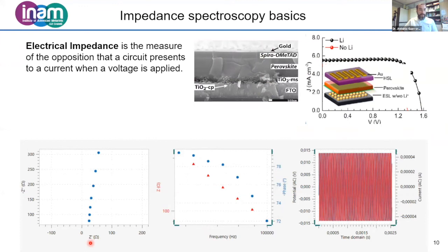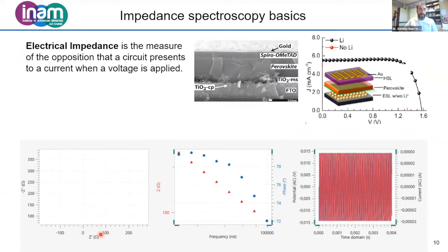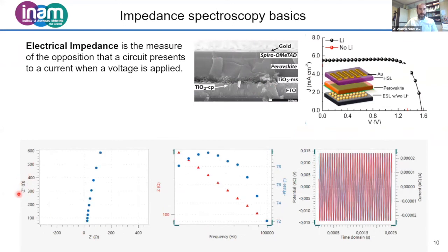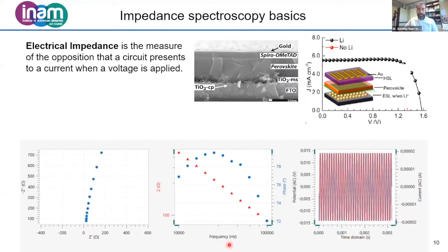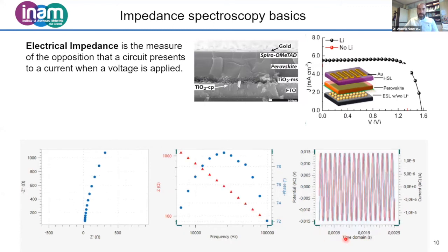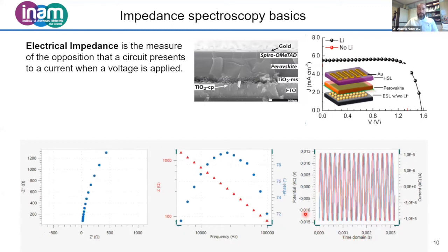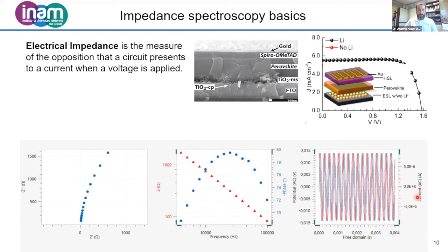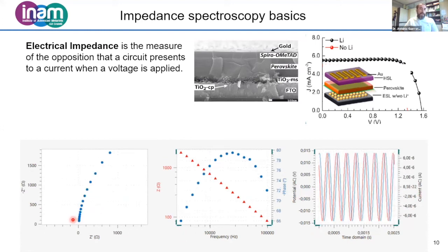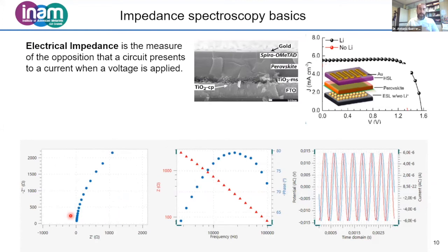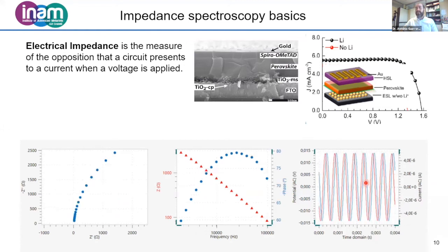First one, this is the complex impedance plot, where we represent the real part of the impedance versus the imaginary part of the impedance. Here we have the total impedance of the device versus the frequency. And in this one, we have the temporal variation of the applied voltage perturbation with respect to the current that we measure. Usually we start at high frequencies of about 1 megahertz, and then slowly we go to lower frequencies. Now we are at the lower frequencies, and this is why you can see the sinusoidal wave.